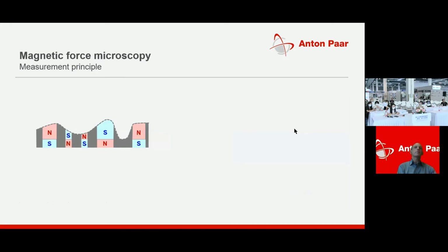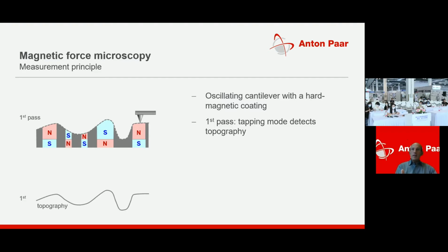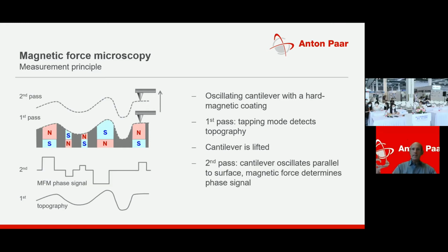But this is the mode of this magnetic force microscope that we have used to characterize the material surface where we expect different magnetic domains. For this purpose, we use an oscillating cantilever with the atomic force microscope tip covered by a hard magnetic coating. In the first pass, the cantilever is operated in the classical tapping mode and detects the surface topography. Afterwards, the cantilever is lifted, and in the second pass, the cantilever again oscillates, but now parallel to the surface at a constant distance. The magnetic interaction between the cantilever tip and the magnetic domains of the material determine the final phase signal.